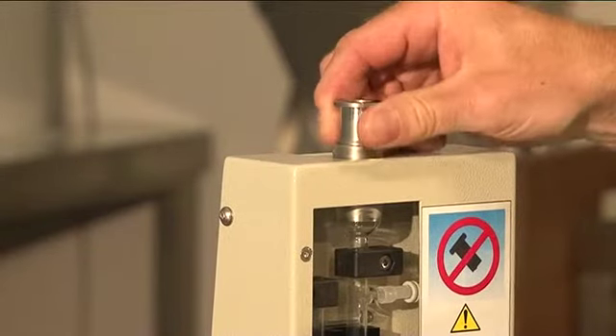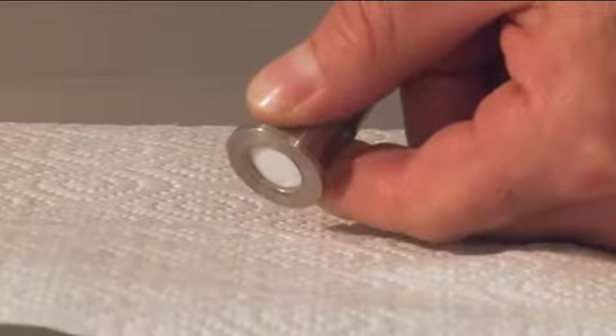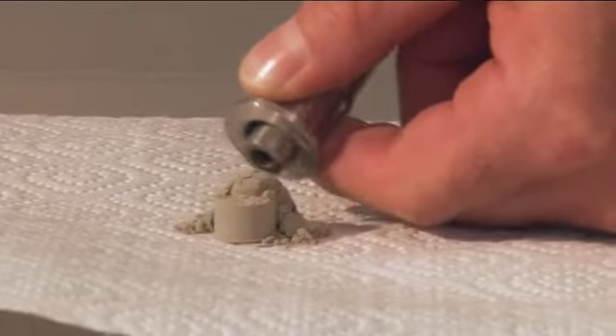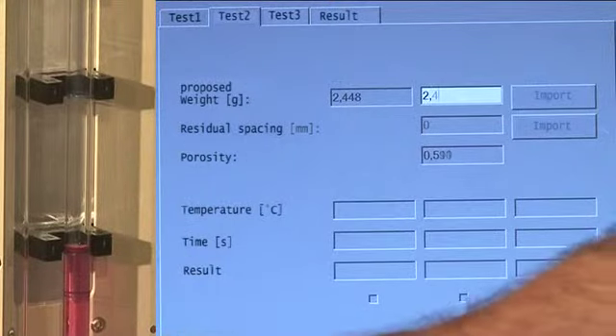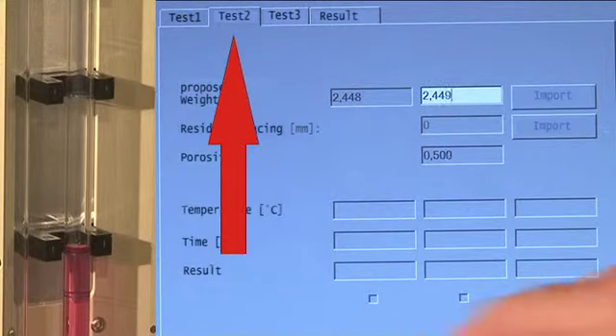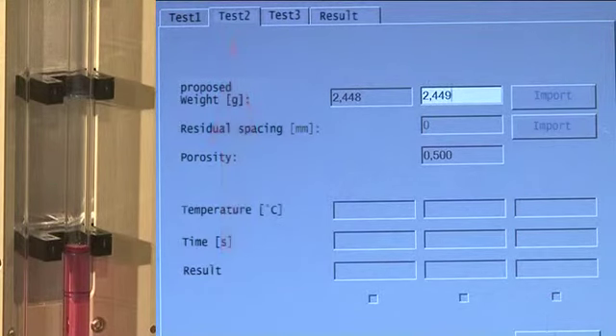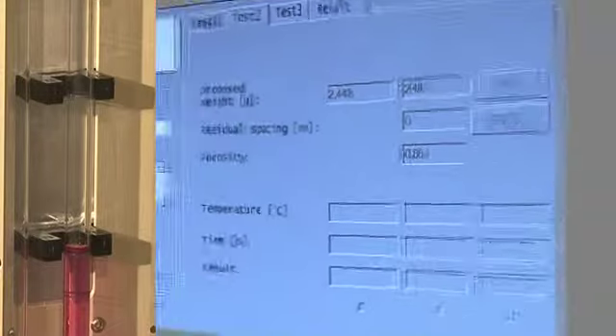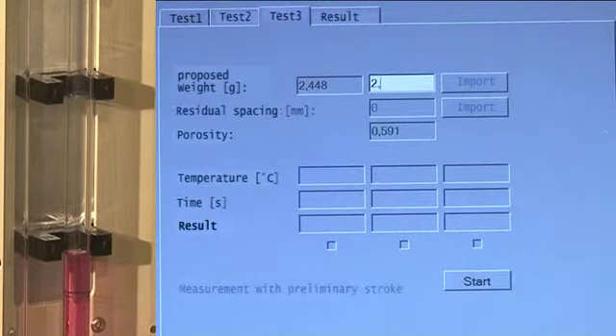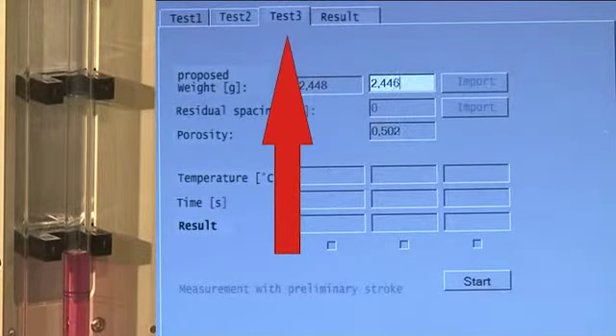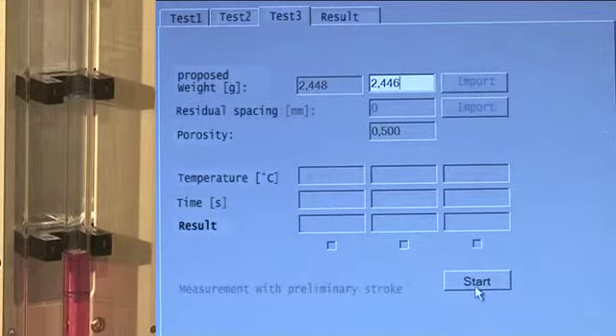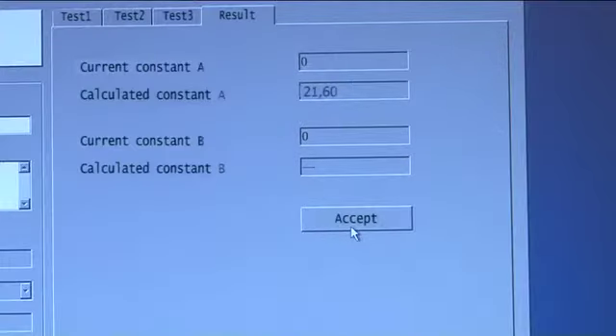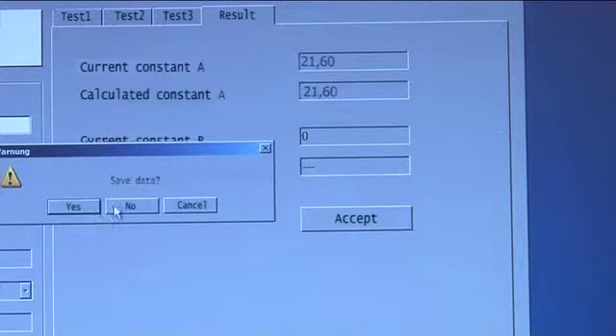After the third measurement, the measuring cell is removed from the glass cone and a second sample is prepared. This is then also tested 3 times. Finally, a third sample is prepared from the reference substance and also tested 3 times. The mean value from the 3 tests is calculated from the 3 measurements. The new apparatus constant A for the corresponding calibration substance can be stored by pressing Accept.